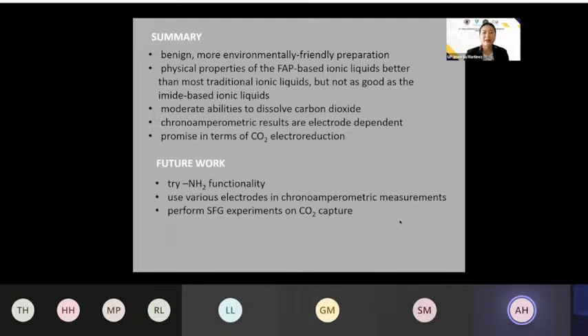So let me just summarize the work that we have done on this particular research work in the lab. So we were able to come up with a benign, environmentally friendly preparation of our ionic liquids, and the physical properties of the FAP ionic liquids that we have synthesized in our labs are better than traditional ionic liquids present out there. But of course, we still have to do better than imide-based ionic liquids. And then in terms of their ability to dissolve carbon dioxide, we can see moderate abilities. And then we've also observed that the amount of carbon dioxide dissolved in our ionic liquids measured using chronoamperometric results are dependent on the electrode. And of course, this particular research really has a lot of promise in terms of carbon dioxide electroreduction, which is very important in the industry.